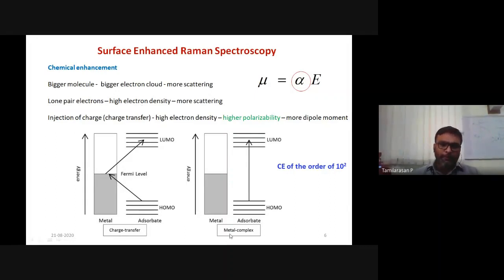And there also they are proposing two different mechanisms. One is the charge transfer mechanism, where the metal surface, the plasmonic surface, and the molecule are in contact. The metal surface transfers an electron to the molecule, and later it will be compensated by the molecule. So this is the charge transfer mechanism. And secondly, they are also proposing a metal complex formation mechanism, where the metal and molecule form a complex, and because of that, the excitation is assisted. Generally, as we have already seen, the electromagnetic enhancement mechanism will practically go up to 10 power 10 times enhancement, and the chemical enhancement will go up to 10 power 2 times enhancement in the Raman signal.